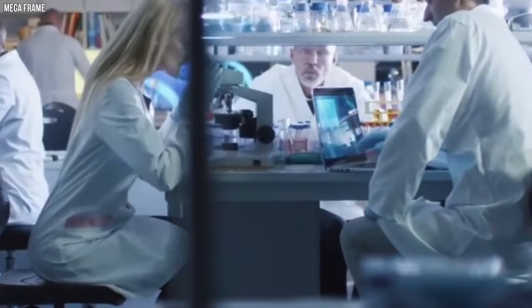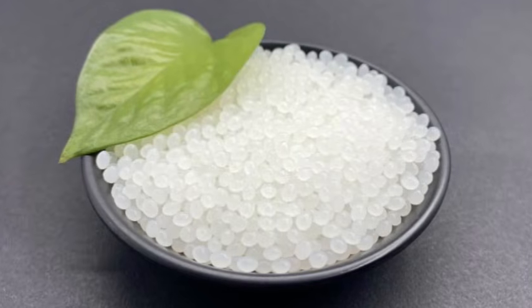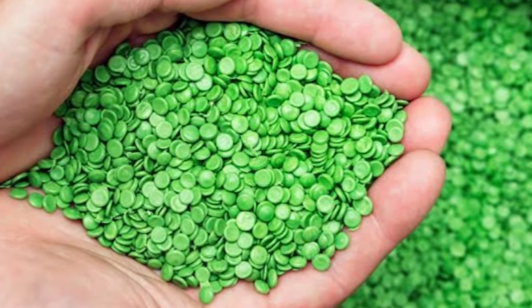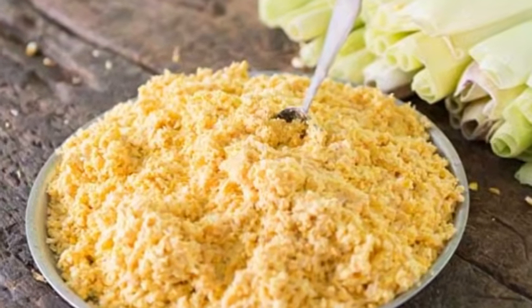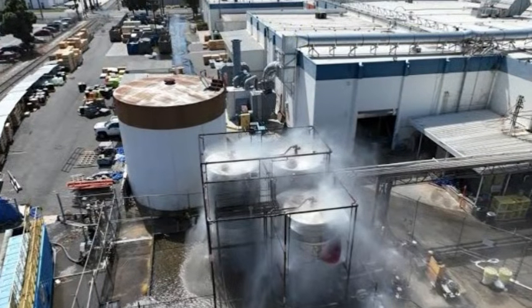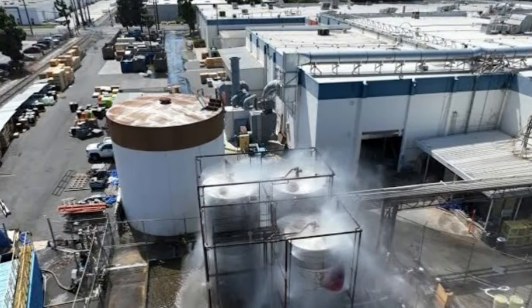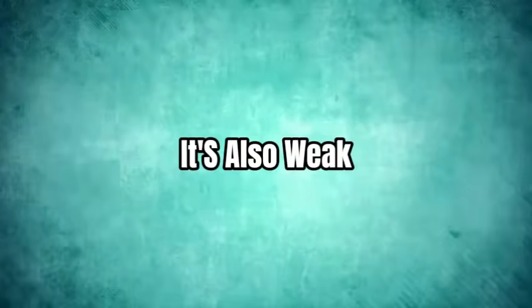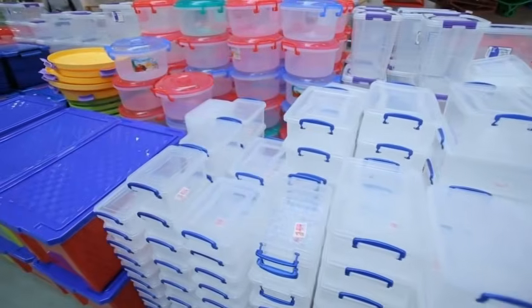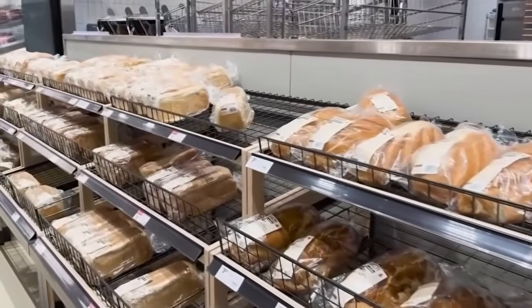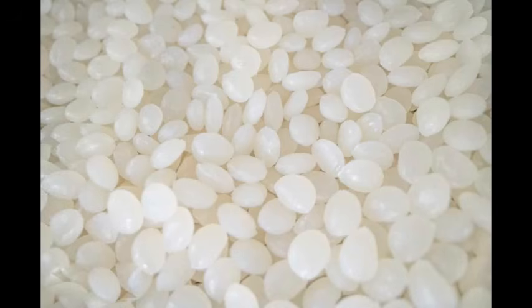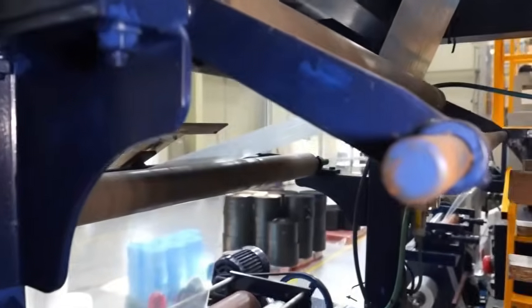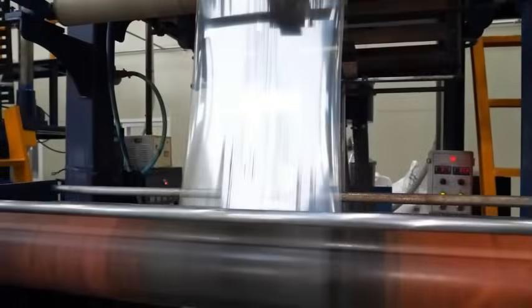It doesn't break down. For decades, scientists have tried to fix this, and almost every attempt has failed in the exact same way. Take PLA, the most common bioplastic, made from fermented corn starch. It only breaks down inside special industrial facilities held above 58 degrees Celsius for weeks. It's also weak, it can't handle heat, and it eats up farmland that could be growing food instead. Then there's PHA, which breaks down more easily but costs several times more than regular plastic to produce. So it's been stuck in tiny niche products for years.